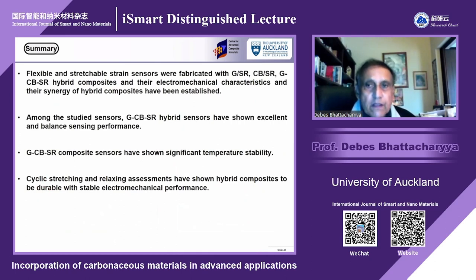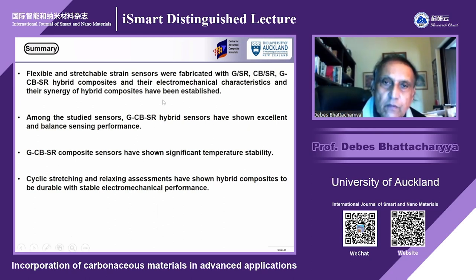If we summarize what we have discussed, flexible and stretchable sensors were fabricated with graphene silicone rubber, carbon black silicone rubber, and graphene carbon black silicone rubber. The first two are single-filler composites, but the third was a hybrid composite. Among the studied sensors, the graphene carbon black silicone rubber hybrid sensors have shown excellent and balanced sensing performance.